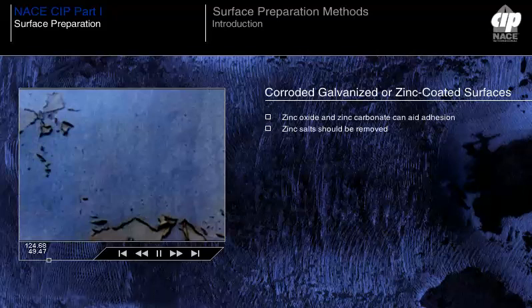Zinc surfaces should be lightly blast cleaned, brush blasted, to roughen the surface prior to painting, or treated with an acid-based solution, for example, acid etch primer or acid wash solution, to provide a clean surface with a profile. Either of these treatments will enhance coating adhesion to the substrate. Current thinking suggests that better results are obtained by blast cleaning before coating rather than relying on etch primers to provide good adhesion.